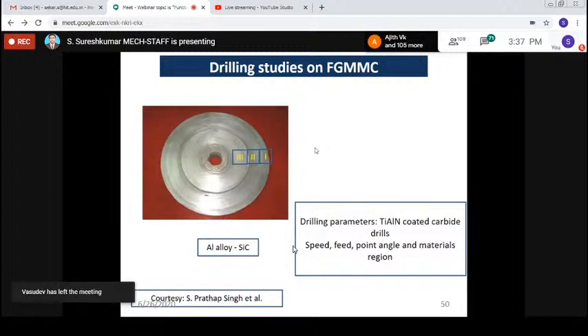They changed the drilling process, using coated carbide tools with some input parameters, right? And some variation in the measurements. What is the surface roughness produced at the three different regions, they have pointed out. As I told you, at the point where the reinforcement is rich, there is more resistance to metal removal, so it will end up with a poor surface finish. And of course, it produces more thrust force also.